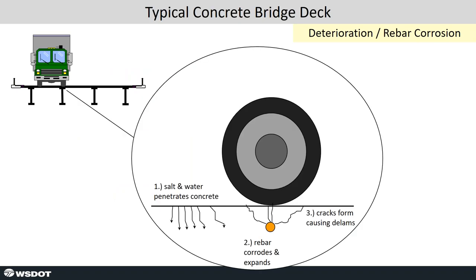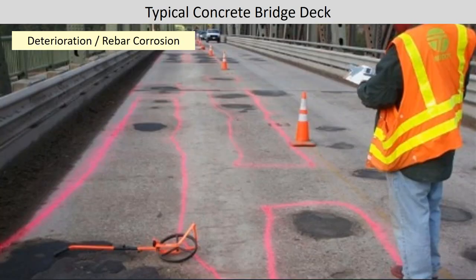So as far as deterioration, rebar corrosion, the whole mechanism is basically salt and water gets down to the rebar. The older rebar with no corrosion protection, no epoxy coating, would rust, and then it would form cracks, and then truck tires would hammer at it and cause potholes. Here's a picture of a typical deck where the pink shaded areas are areas that are delaminated based on a chain drag survey. The other areas were temporarily filled with some material by maintenance. So you can see in this particular bridge, the deck is really deteriorated and needs some type of attention, and it's due to rebar corrosion.